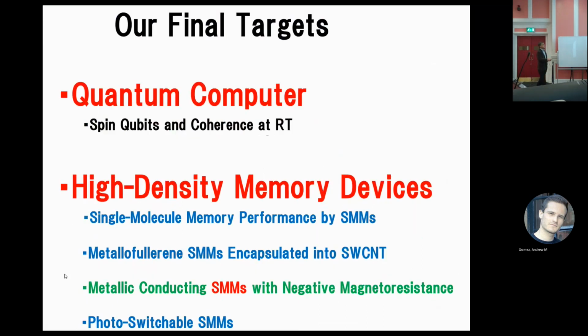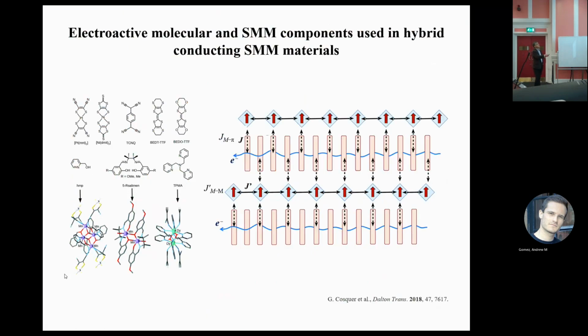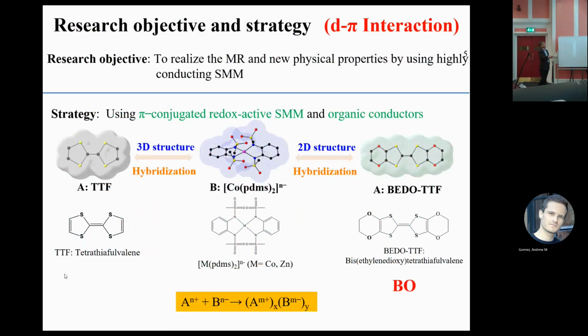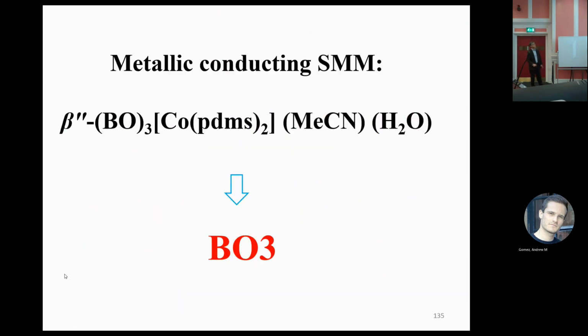So let's put the metallic conductive single molecule magnet with negative magnetoresistance. We usually use a single molecule magnet to overcome Moore's limitation. So many organic conductors, and we use a single molecule magnet. Conduction electron and localized single molecule magnet interact to show the giant magnetoresistance, negative magnetoresistance. For this purpose, we usually use BEDO-TTF. This shows superconductivity or metallic behavior, and also the acceptor is a cobalt single ion magnet. We put in both, and by the electrochemical method, we obtain the conductive single molecule magnet. So this is beta double prime BEDO-TTF and cobalt PDMS in this material.